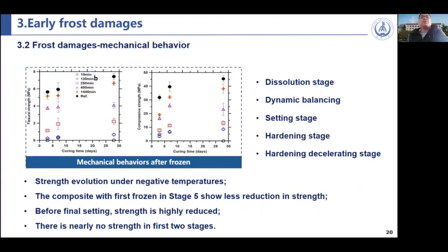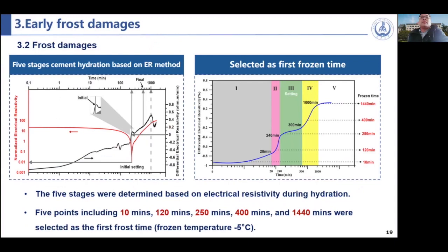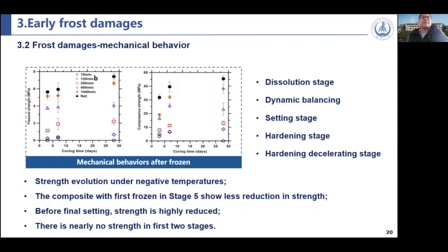And then we put the cement paste under the standard curing condition and at the relative time, we move the sample to the negative temperature, so that the frost damages will appear in the cement paste. This is the mechanical behaviors after frozen.